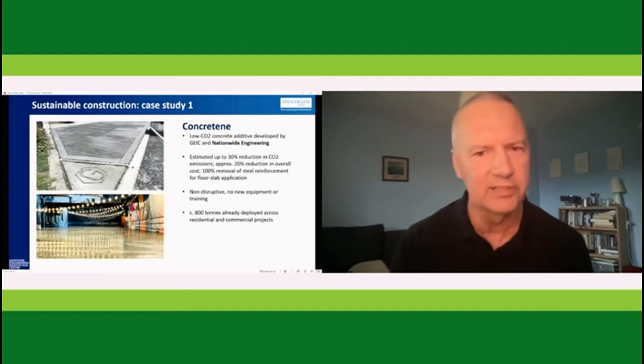So a lot of interest around the potential of graphene enhanced cements, and some very interesting trials taking place around the world in terms of reducing the amount of cement or concrete. Because if we can use 30% less, that would be a global reduction in CO2 of around 2–3%. So of great interest if we can achieve that.